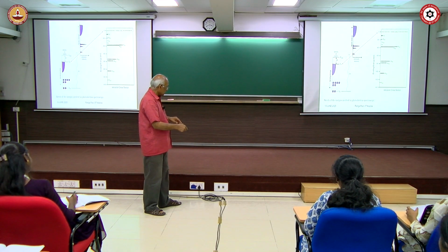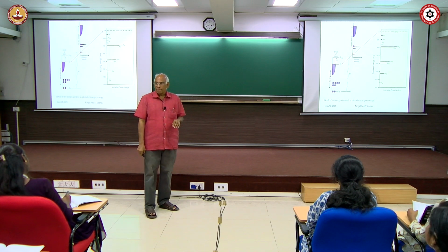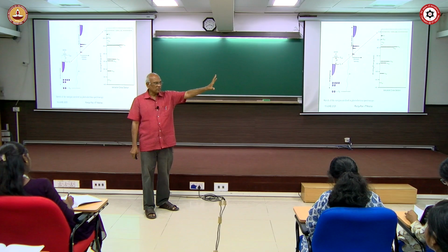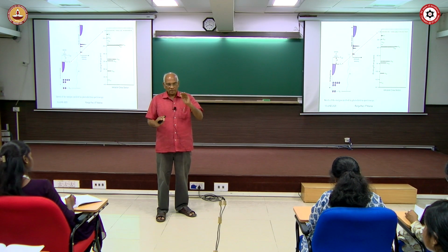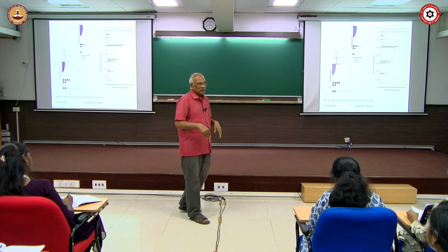Okay. So your spectrum should look like this. Now the intensities are different here, you see. These intensities are different because of something called the ionization cross section. Suppose I have 2 electrons in one orbital, I have 6 electrons in the p orbital, and 10 electrons in the d orbital, right? So I should get more intensity. No, there is something called the photoionization cross section. If the ionization cross section is high, your intensity is going to be high, otherwise it is low. Cross section is nothing but the probability of absorbing the photon. Okay, all right.